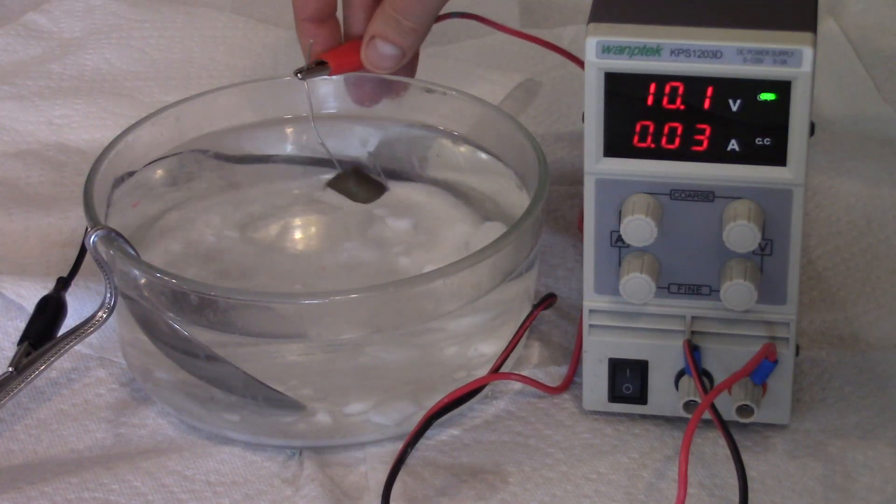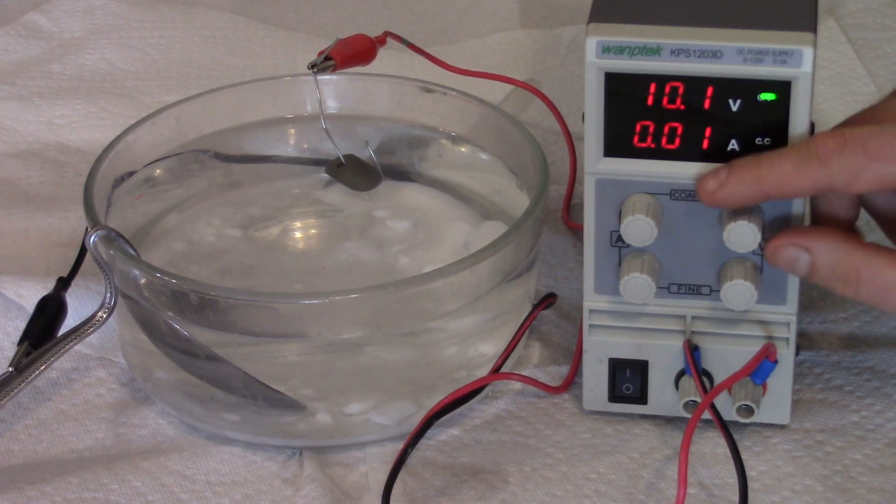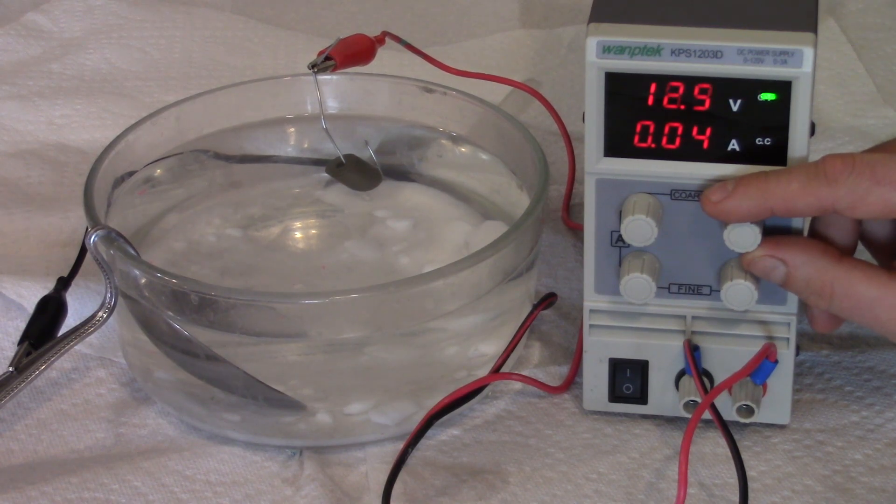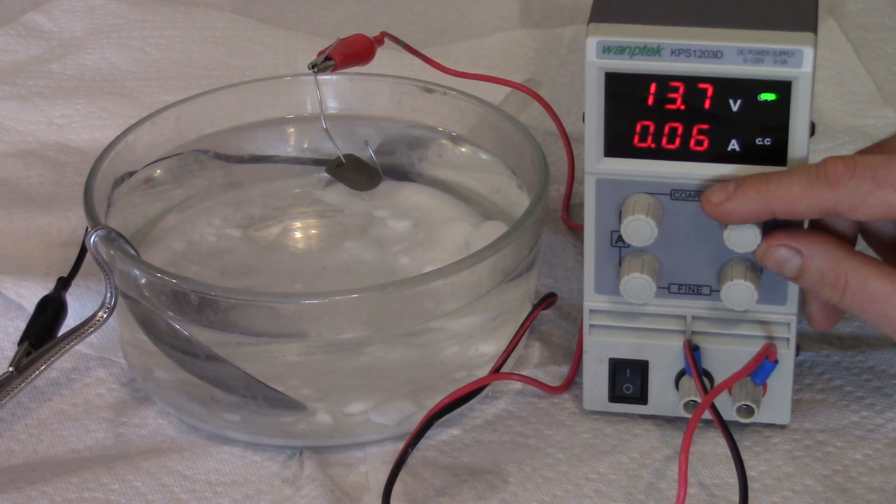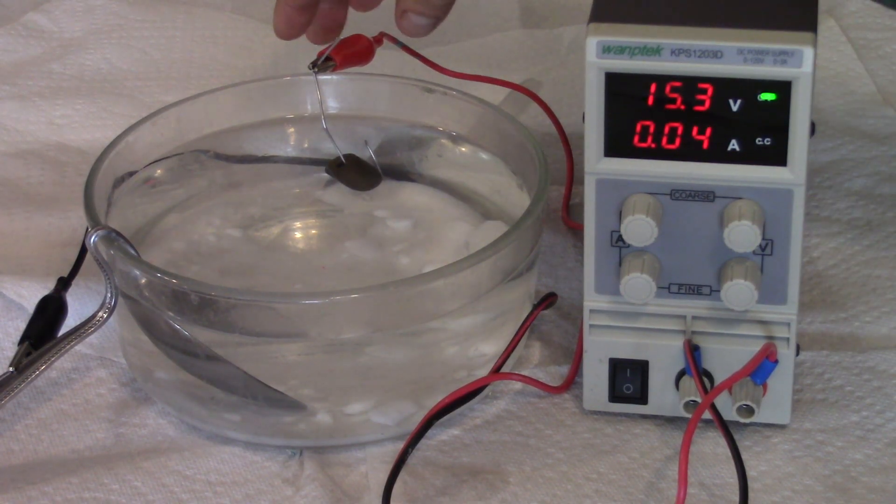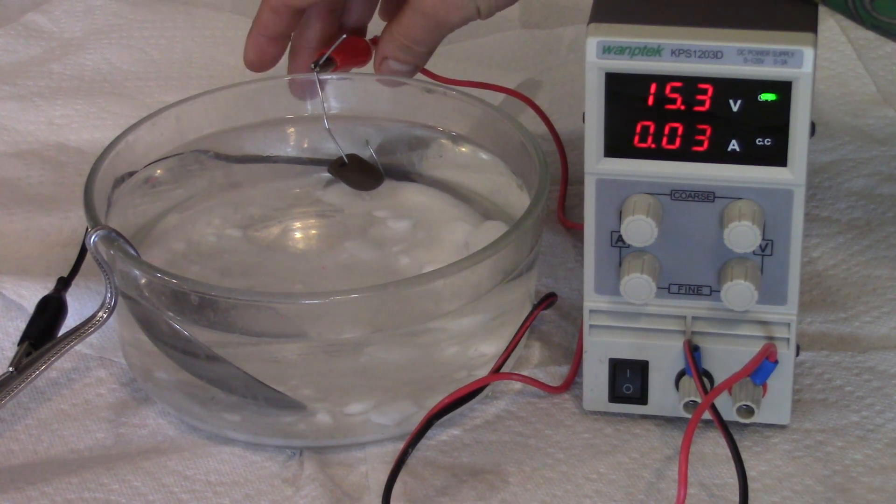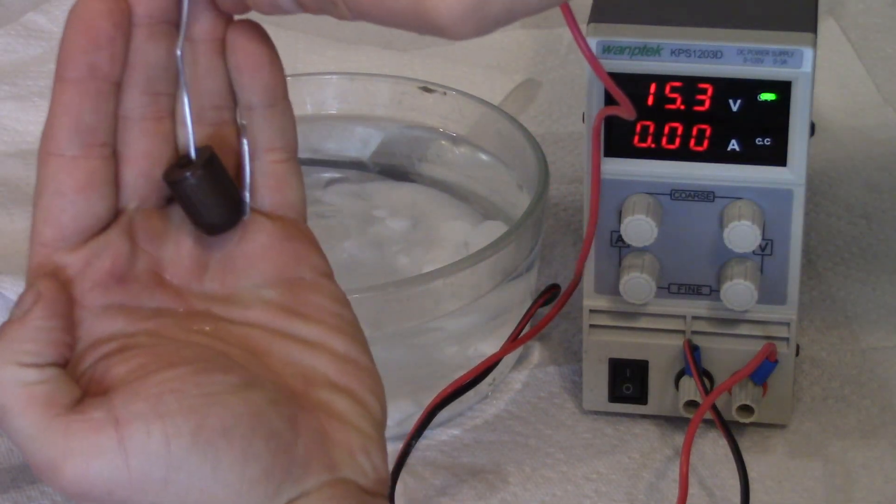Then it starts, you start getting a little darker, 10 volts and starts to turn slightly brownish. So as we go towards 15, it's gonna get darker shades of brown. So 10 to 15 is where you're gonna get a lot of your brownish colors. See, as we slowly get towards 15, that's a nice real dark brown. I don't know why you'd want to anodize brown, but...